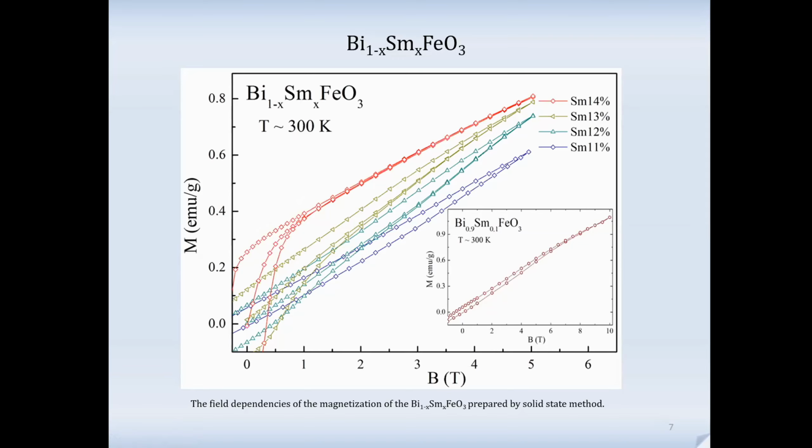It's really small magnetization. This can raise the question of why we have remnants inside the antiferromagnetic state, if it's not strongly collinear. There is some really small inclination because of the Dzyaloshinskii-Moriya interaction, and this is the origin of the really small, but still existing, remnants.